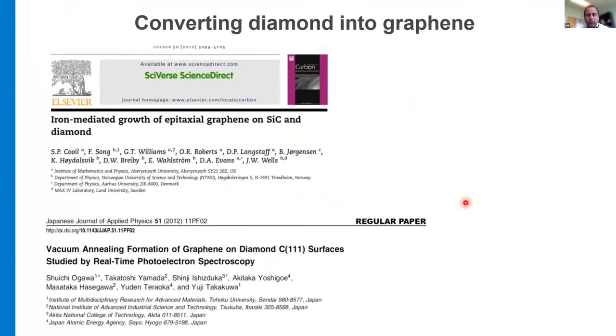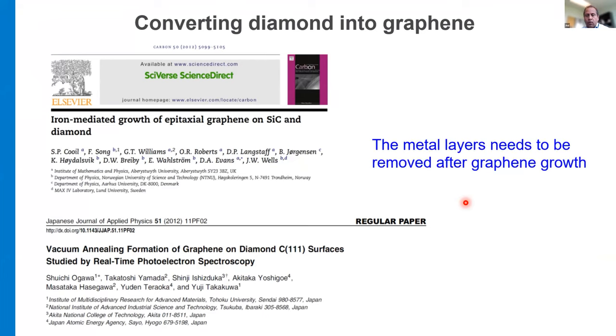Now the question we were looking at is, of course, we did the exfoliation of the graphene and then stacking directly onto the diamond. We wanted to see if we can convert the diamond into the graphene. There has been some work done in the past utilizing iron for making graphene on diamond and silicon carbide. Also annealing diamond at higher temperature gives graphene growth.